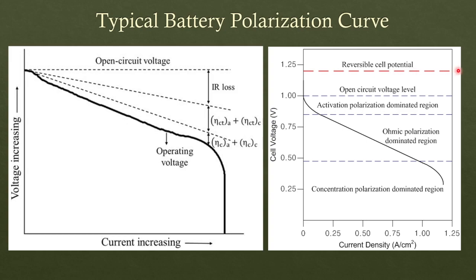If we look at the right image, you can see there is a reversible cell potential which we don't typically use because of safety reasons. So we try and limit it to some smaller value or lower value based on limiting the upper and lower cutoff voltages of the cell. For example, in a lithium-ion cell, for instance NCM graphite cell, will have a voltage window of 4.2 to 2.5 typically.